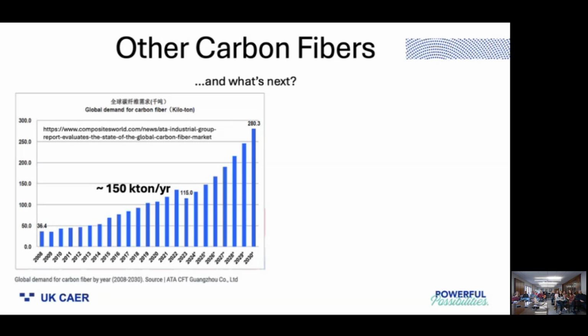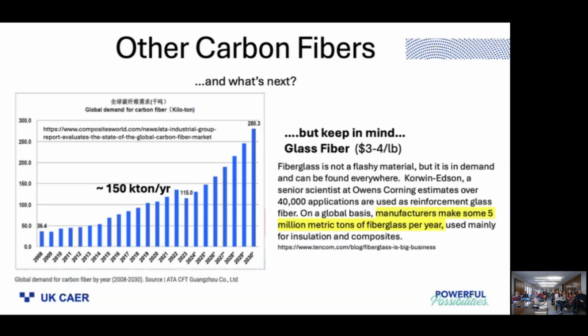That might sound like a lot, but if we look, for example, at glass fiber, something like 5 million metric tons of glass fiber are produced each year at a price of somewhere around $3 to $4 a pound. That's about an order of magnitude cheaper than carbon fiber, and there's far less carbon fiber out there. But remember, glass fiber can be melt spun just really fast relative to carbon fiber.